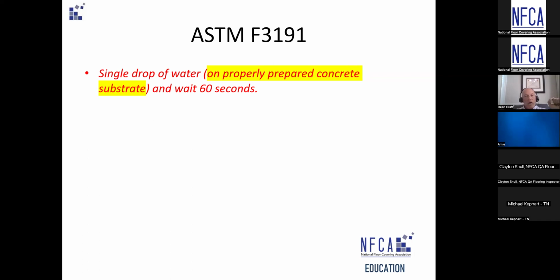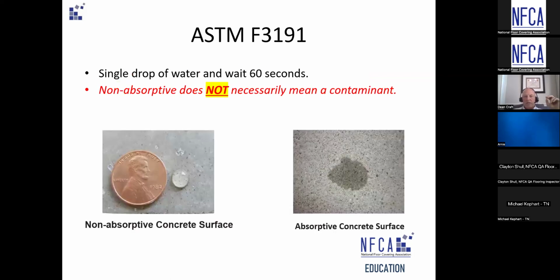Now, that includes prep material. If you're going to skim the entire thing, do the test, follow the instructions for the skim coat material, then you have to test again. You can't assume any layer you put on there; you have to keep testing. Usually the biggest one would be a skim coat material. Don't assume that skim coat is going to be absorptive. I've seen plenty of them that are not. Doesn't mean they're bad. Just don't assume. It's a quick test. It's the quickest test you can do.